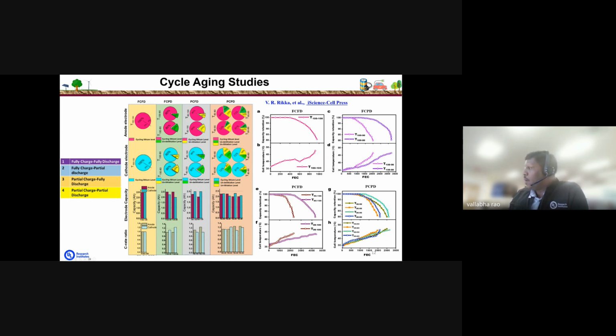But generally, in all electric vehicle applications, we will go with the partial charge and partial discharge. But if you compare the cycle life, it is still lower than even the full charge and partial discharge. So this is one of the new findings in our studies. And again, if you consider one charge per day, 900 cycles means 900 days, which is almost equal to 3 years of lifetime.